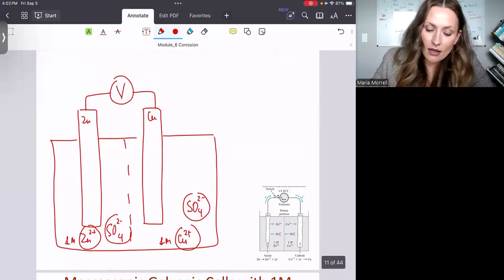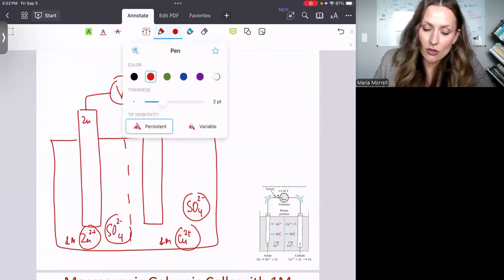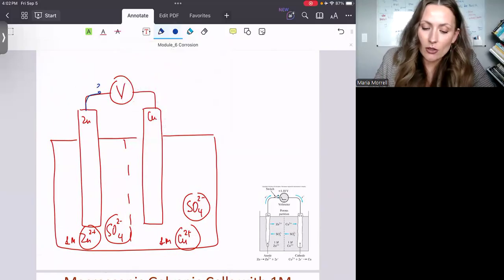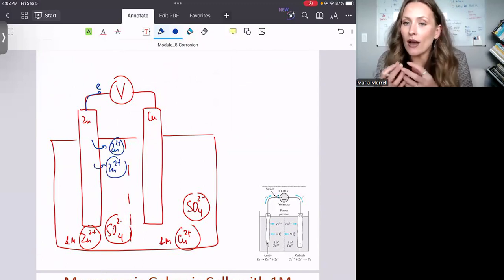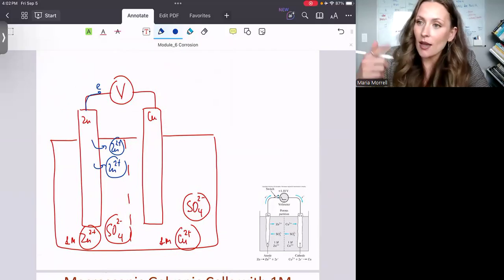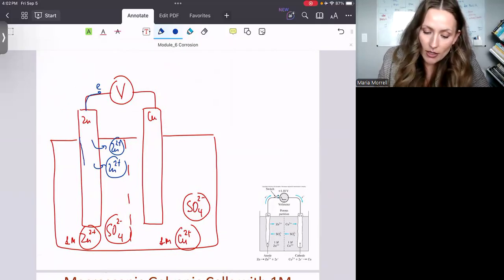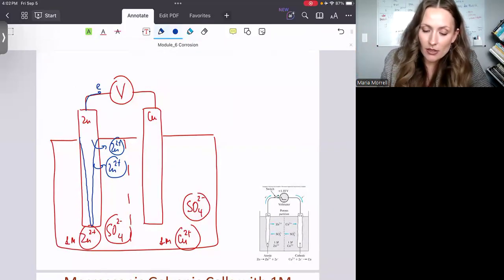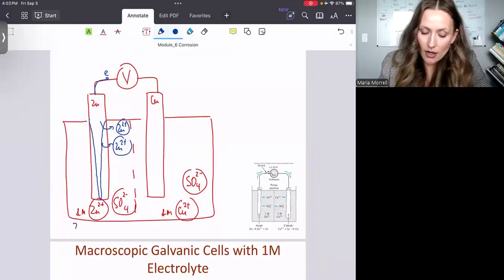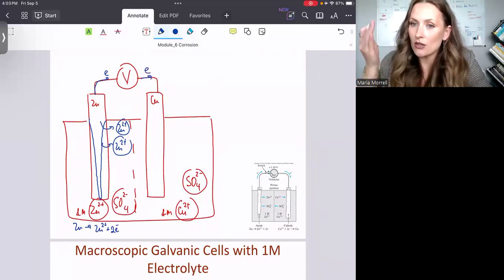That means that zinc is going to lose its electrons, right? And if it loses electrons, you have a bunch of zinc that is leaking into the system, right? And what we mean by that is that you have disintegration. So as time goes by, within this electrolyte, my zinc gets thin and thin, right? It's like the target just disintegrates and you can probably see it. And the way it occurs is that zinc goes to zinc 2 plus and releases these electrons. The electrons continue traveling through the circuit, assuming that the circuit is closed.